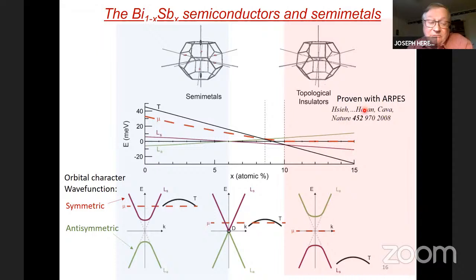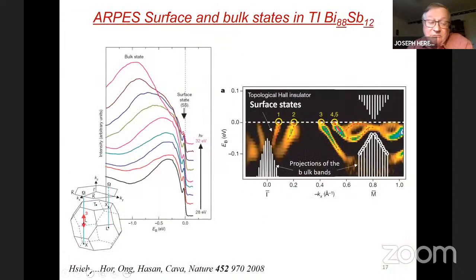In fact, it was the first topological insulator identified experimentally by ARPES. I will show you these data here. This was Hsieh and Hasan back in 2008. And here are the ARPES drawings of the surface states of these topological bands in this bismuth antimony, 88%, 12%. So this is really a TI. The beauty of it is that it can be made insulating. It's a genuine topological insulator. There's no problem with making that insulating.